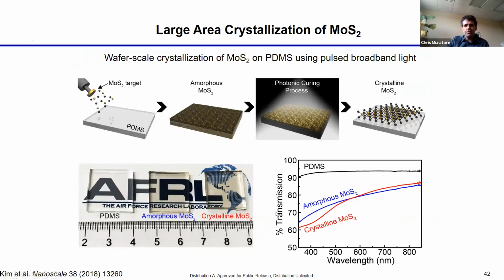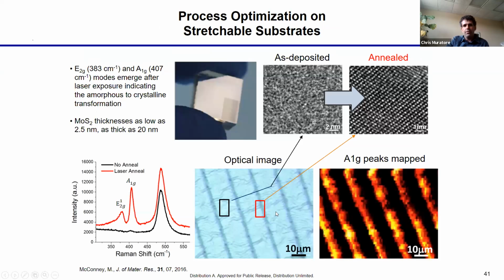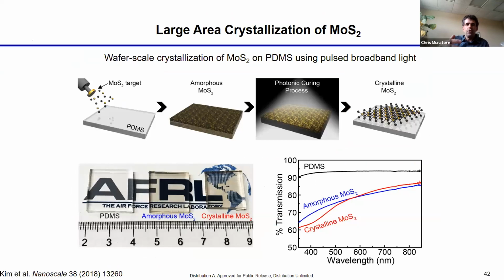And a laser is useful because you can write features in the surface and induce crystallinity of these materials. But the problem with a laser is that the beam width is narrow, right? So these are like 5 micron diameter patterns. These are the crystalline lines in this amorphous material. This is on PDMS. You can see some of those ripples that we talked about before on the surface of this image.